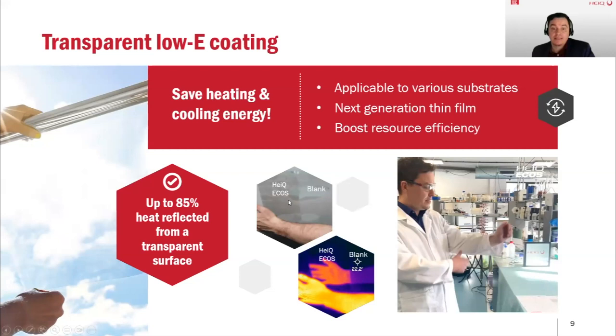First example here is on the left-hand side, a polymer film coated with HeiQ ECOS. On the right-hand side, the blank, the uncoated substrate. And now we hold our hand in front of this area with a certain distance and look at it with the infrared, with the heat camera. And what we see here is where the HeiQ ECOS is present, the heat that is generated from the hand is reflected back from the surface. Whereas on the right-hand side, the uncoated substrate, it appears blue, so no heat is reflected.